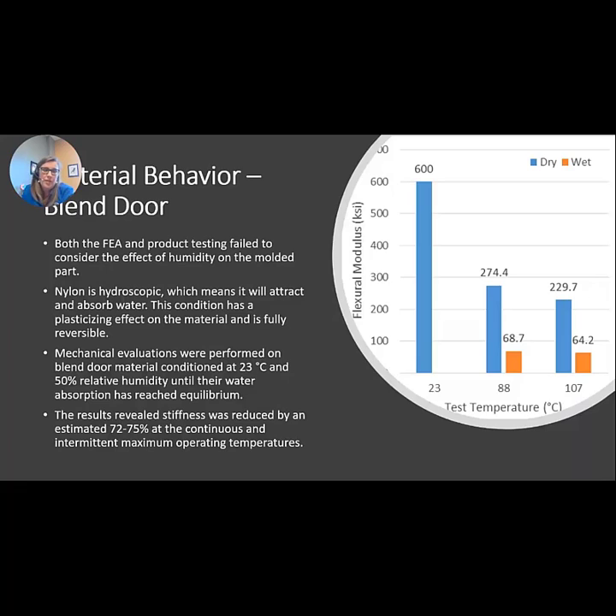So one of the things we did to kind of emphasize this with them was we took a door and we did some flex testing. And you can see here at some of the temperatures that they're operating at that you're getting a significant decrease in stiffness with elevated temperature. But now once you condition that nylon door at 23 degrees C and 50% humidity, the water absorption is decreasing the stiffness of the material by about 75%. So this is a huge impact. And this difference is going to make the difference of your door deforming permanently in the field or not.